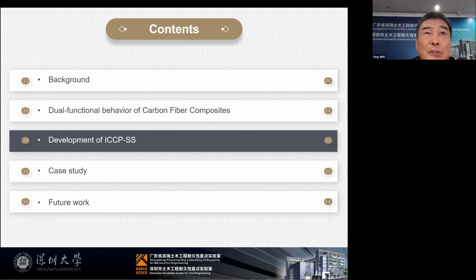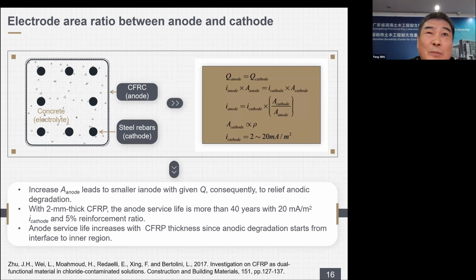Now, I will introduce the development of ICCP-SS. There are some fundamental problems to be discussed. Consider a simple reinforced concrete cross-section. This leads to smaller current density and reduce anodic degradation. Therefore, the most efficient and direct way to increase the service life of ICCP-SS system is to design the larger anode area. This is also the reason why traditional ICCP anode is normally arranged at the outer surface of reinforced concrete.